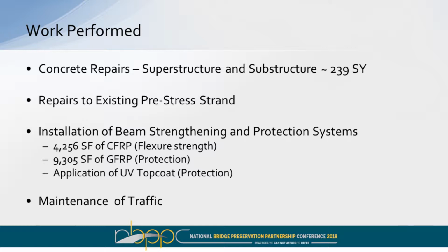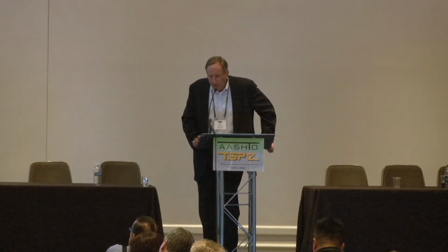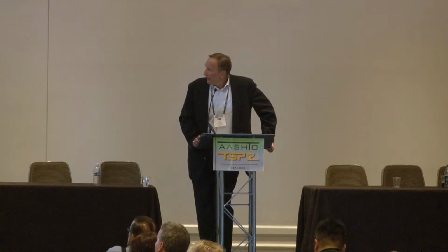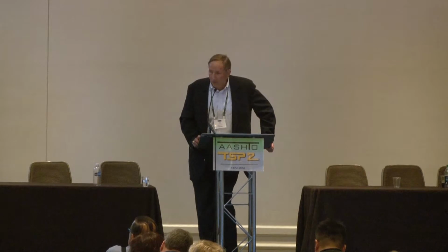And also from a beam strengthening standpoint and also protection standpoint, we placed roughly 4,200 square feet of carbon fiber for flexure strengthening, and also roughly 9,300 square feet of glass fiber reinforced polymer for the protection. In addition to that, we applied a UV top coat over that glass fiber material. And then, of course, one of the biggies, as you could probably tell from those pictures I showed you earlier, was the maintenance of traffic that was key, because at some point we did have to bring construction vehicles onto the deck in order to access the work areas.